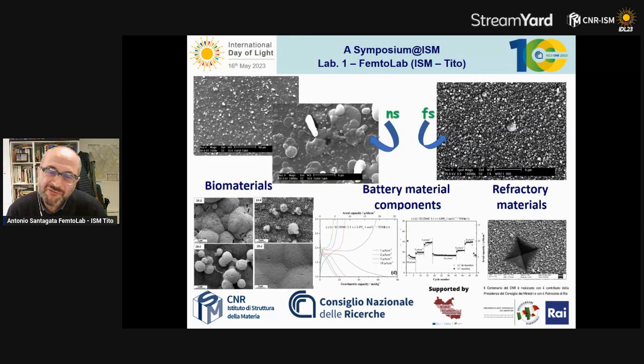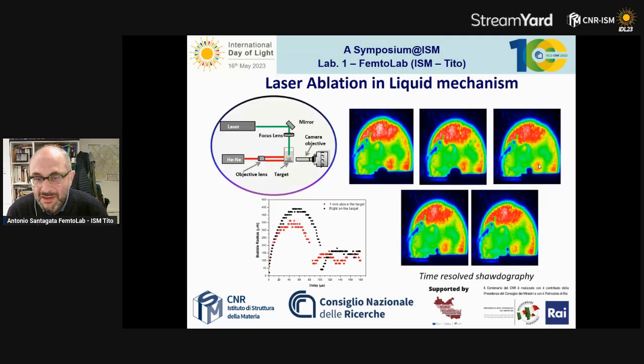The difference between femtosecond and nanosecond is that we can retain the properties of the starting target, and in these circumstances, we can have materials for different applications, for biomaterial, refractory material, battery material components. In laser ablation in liquid, there is another effect, which is the evolution of the plasma, but as well, the process involves first a shock wave and then a cavitation bubble, which is 1 or 2 orders of magnitude slower than the shock wave evolution.